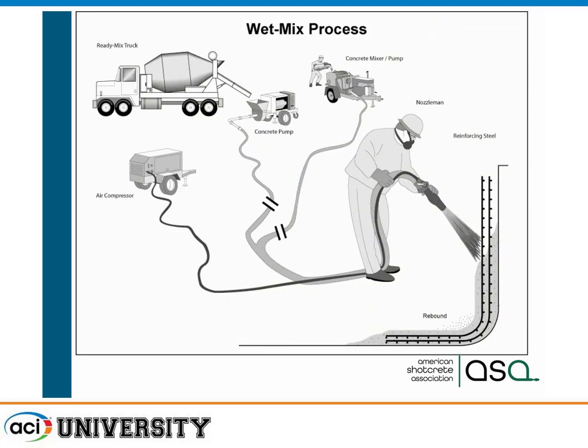The other process is wet mix. Wet mix was developed in the 50s and 60s when we started to get concrete pumps that were more reliable. Most of our pumps are hydraulic cylinder pumps, the dual cylinder pumps that pump the pre-mixed concrete from 1,000 psi to up to almost 2,000 psi through a hose.